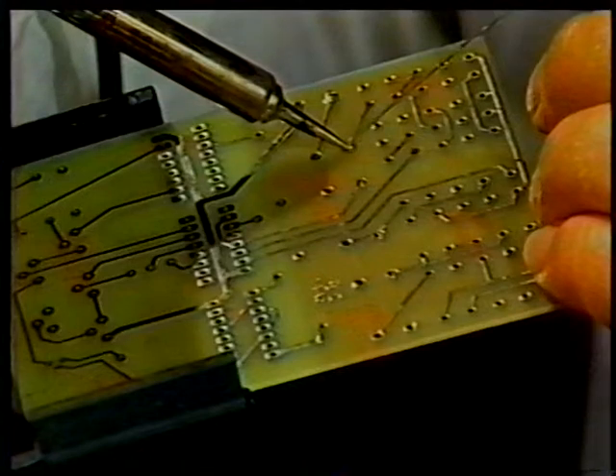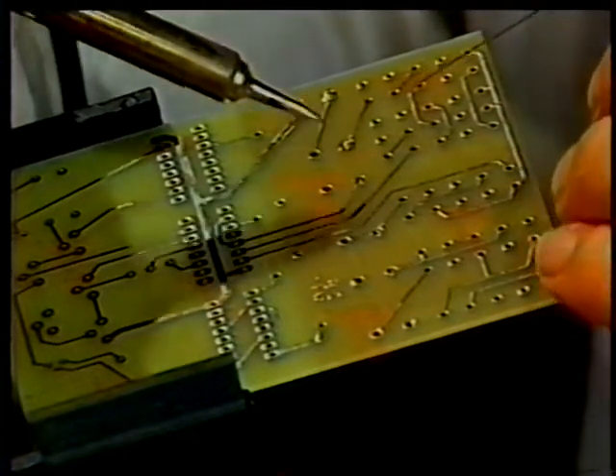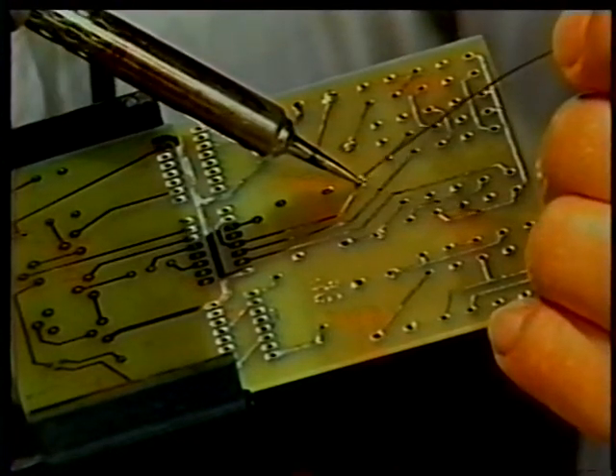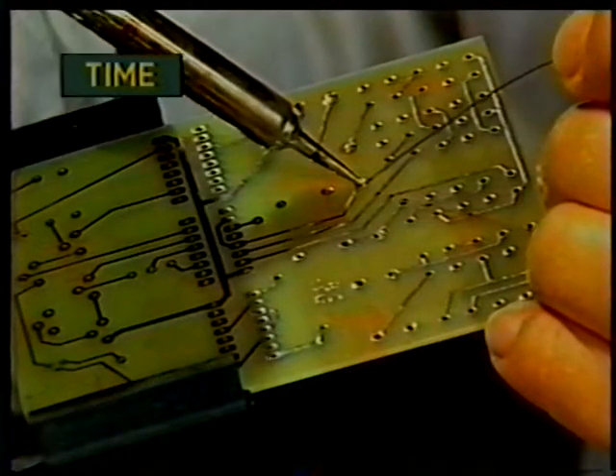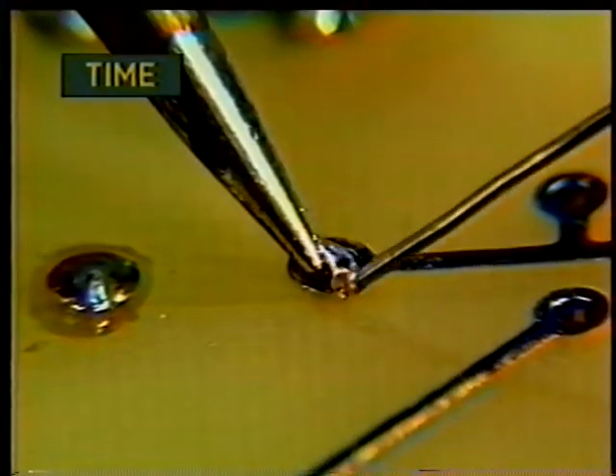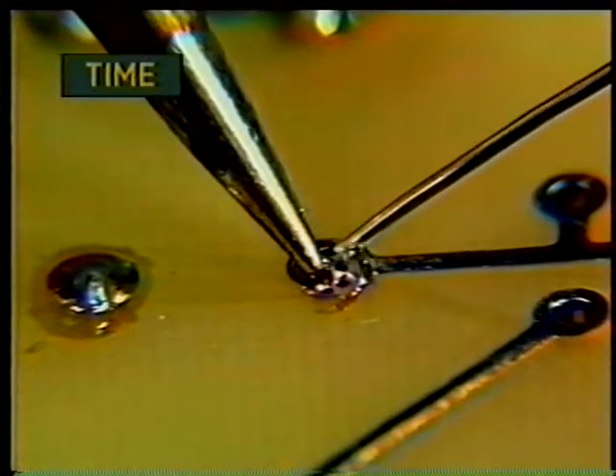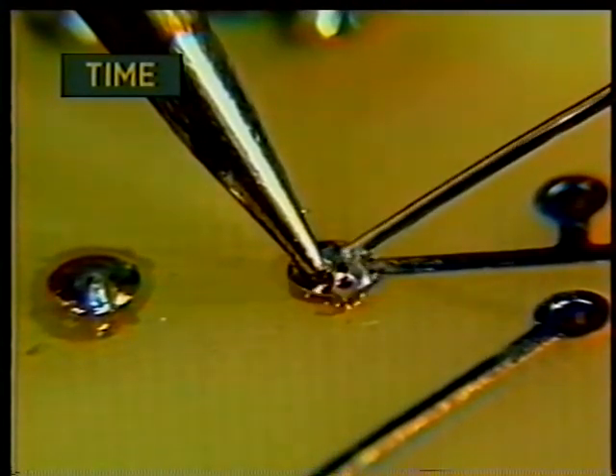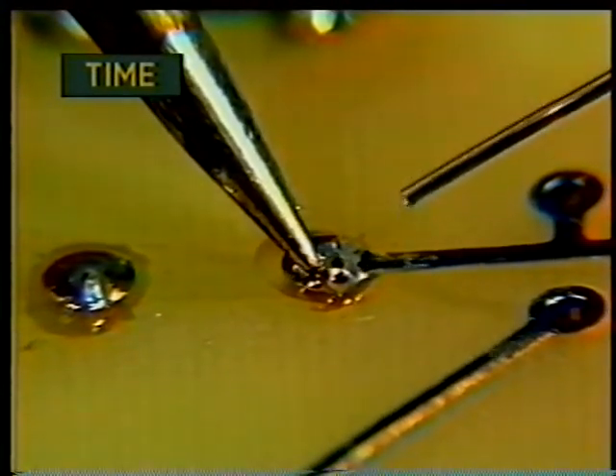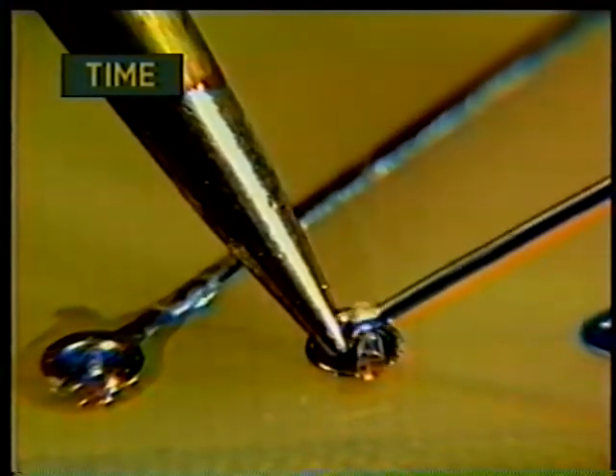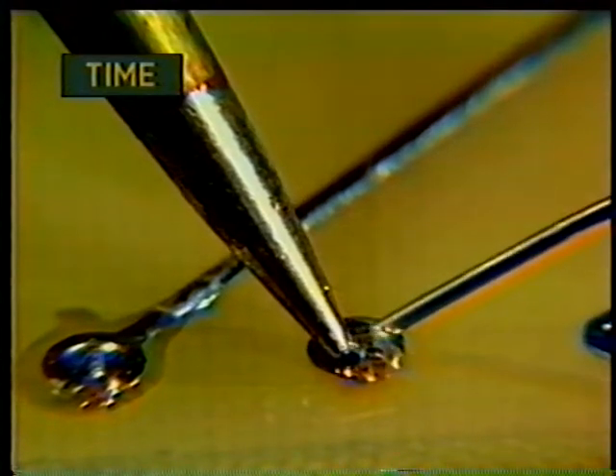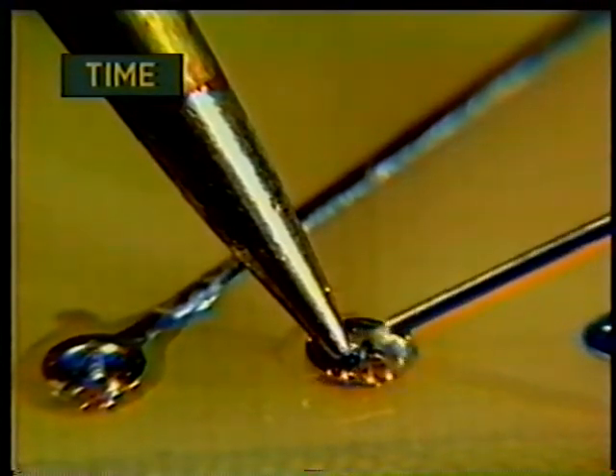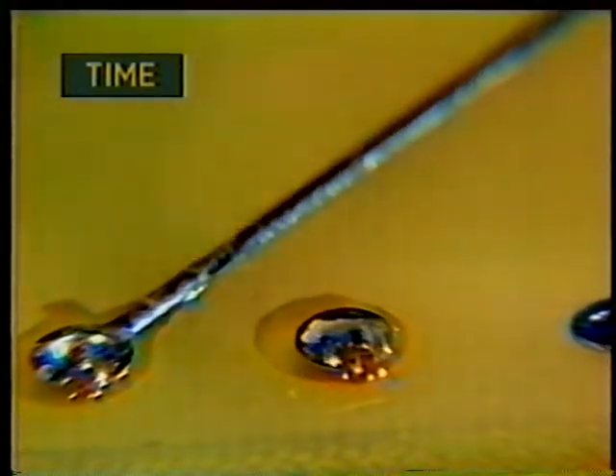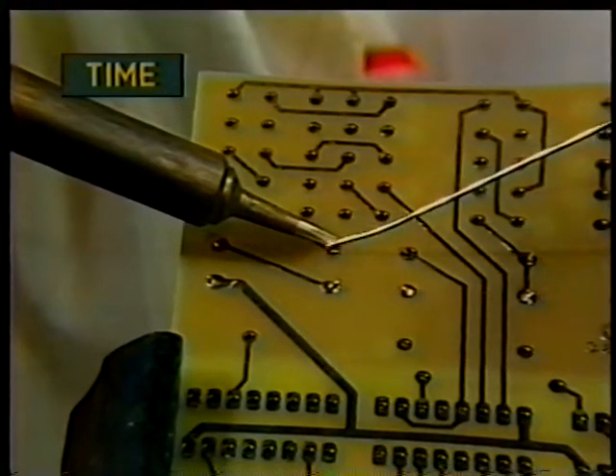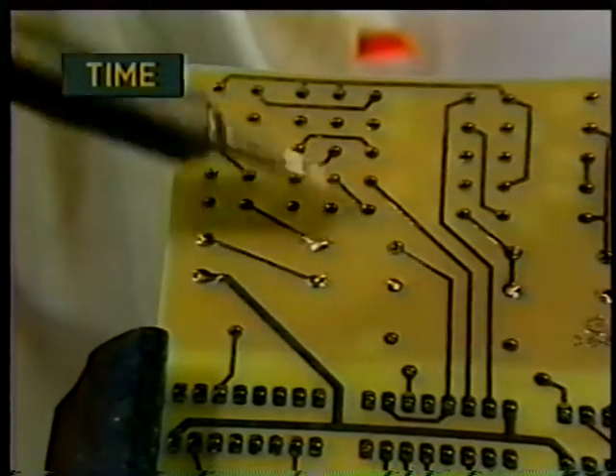The fourth and critical factor to be considered in the making of a reliable solder connection is time. The general rule is, for high reliability soldering on printed circuit boards, apply heat for only the time needed to complete the junction. 2 seconds for thin double-sided boards, up to 5 seconds for thicker multi-layer boards. Keeping the hot iron on the joint longer than these recommended times may begin to damage the circuit board.